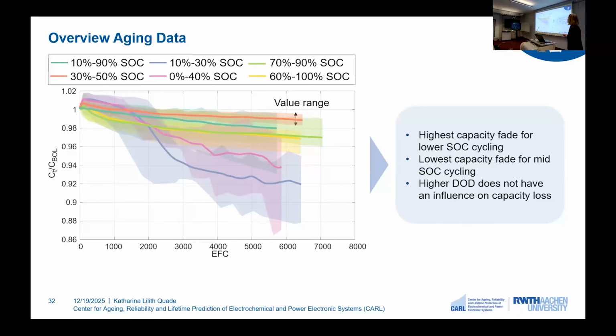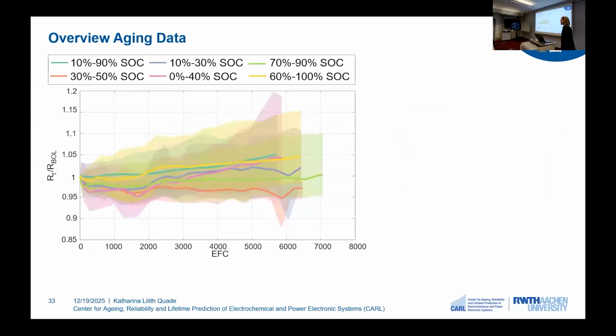We can see, for example, that this purple condition, 10% to 30% SOC, has higher capacity fade, even though the depth of discharge is lower compared to the condition that you can see here in pink. Another important aging indicator is, of course, the resistance. And here you can say the same thing. We see the value ranges and also the mean values.